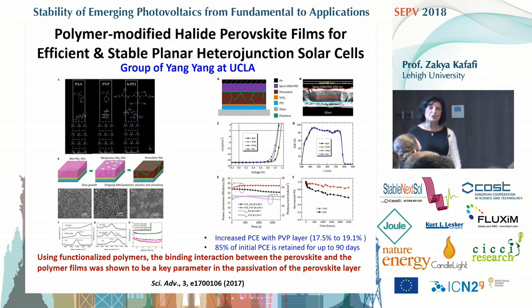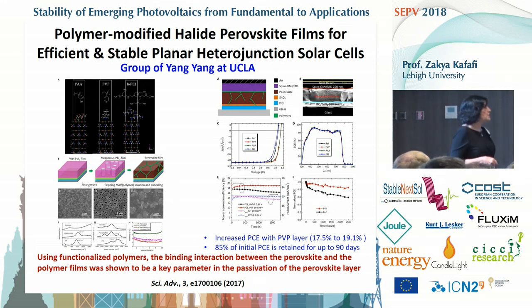Then he realized, like most of us, that perovskites now are the way to go. So he tried to modify the halide perovskite film with polymer, and he was able to obtain efficient and stable planar heterojunction solar cells using this approach. He showed that a key parameter in the passivation using functionalized polymer, which provides a good binding interaction between the perovskite and the polymer film, was a key parameter in the passivation of the perovskite layer.